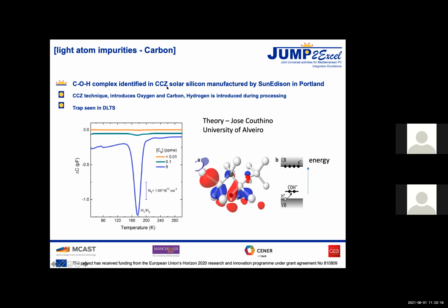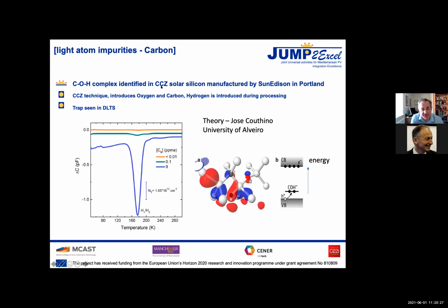And they developed this technique, which is one of the contributions to the cheapening of solar silicon, called continuous Czochralski. What normally happens in Czochralski is you grow a single ingot, you take it out, you saw it up, you empty out the crucible, you refill it, you melt it again, and so on. That's obviously a slow and more involved process. What they do in continuous Czochralski is they just keep on growing the ingot. They pull it to a certain level, they saw it off, and then they carry on pulling. And this cheapens the process.